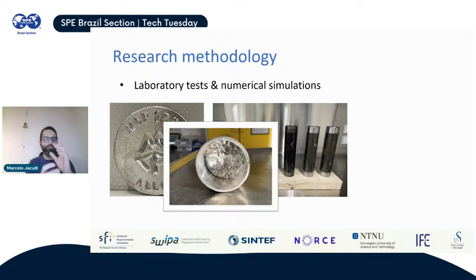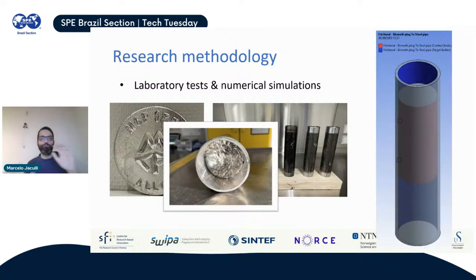And then we take this pipe with the plug inside, and we go to the machine to perform the hydraulic push-out tests. So basically, you're applying pressure at the top of the plug, and then you see how much pressure it can withstand. Or you also measure the leakage rate through the pipe, so you can collect fluid at the bottom and see how much is leaking. And then we take this to the software, and we try to match the laboratory tests with the numerical model. So if you are able to match the results in laboratory conditions, then we know that we have a good material model for bismuth. And then we can hopefully use this simulation knowledge to simulate other conditions that cannot be easily tested in the lab.